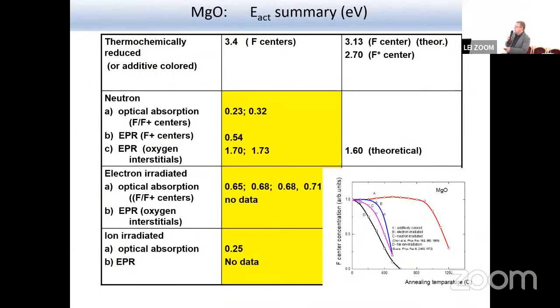But let's go further. This is a kind of summary of the results obtained for MgO. We know the behavior of almost all defects in this classical material, obtained by EPR and optical absorption. Why, for example, is EPR important? All of you who have performed measurements using an optical spectrometer know that at high defect concentration there is saturation of the signal. In this case, EPR is quite important because we can measure the signal at much higher concentrations than by optical absorption.